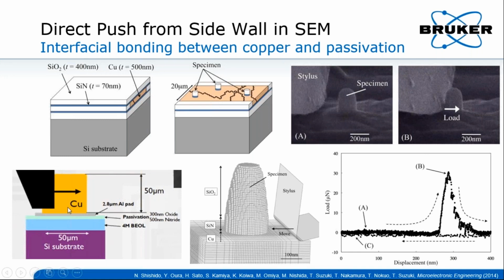The idea is to finish all tests in one SEM chamber. Therefore, the sandwich structure of the sample was designed to have the passivation layers as the top layers and the copper layer as the under layer.